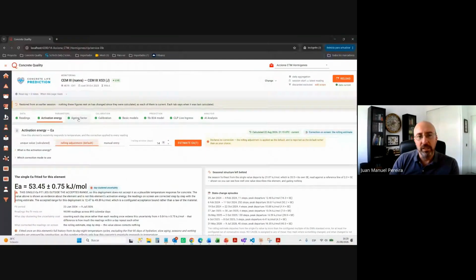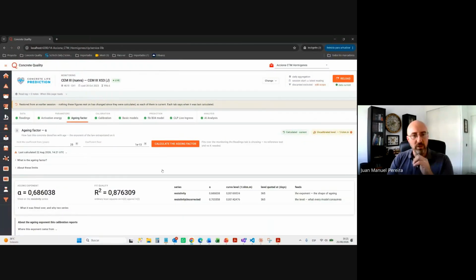Then we have the aging factor. The aging factor is one of the critical parameters that all of the durability models use to predict how the concrete will evolve over time. This is usually tabulated. It's known that for different cement types, for this cement type, the typical value is 0.6, ranging from 0.5 to 0.7. We actually measure this in our concrete in this exposure, and it's almost 0.7. And this is an exponent. I will show you the equations later. So this small change from 0.6 to almost 0.7 has a huge impact on the prediction.